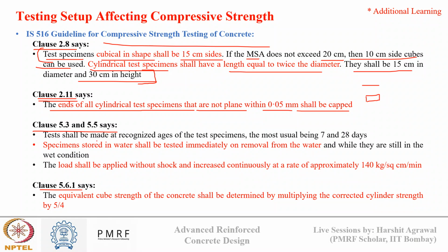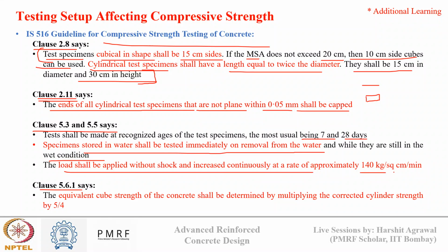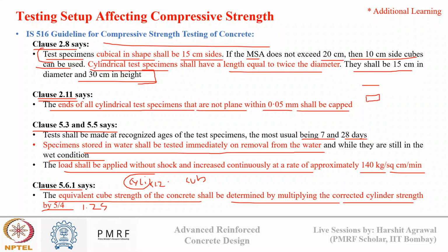Clauses 5.3 and 5.5 say that the strength testing should be done at 7 days and 28 days. It should be stored in water immediately after removal from mold and stored in wet condition until the testing is done. Loading shall be applied at a very specific rate of 140 kg per centimeter square per minute. And if we are doing a cylindrical sample testing and a cube sample testing, the strength will be different. So the equivalent cube strength of concrete shall be determined by multiplying the corrected cylinder strength by a factor of 5 by 4, that is 1.25. So if we get the cylindrical strength, multiplying it by 1.25 will give us the equivalent cube strength, in terms of what we want to report.